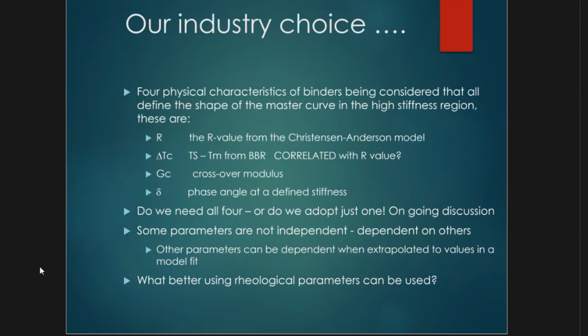And then we have the delta Tc. I think I've heard about that. The delta Tc, you can see here, is a difference between a critical temperature for the stiffness and the m-value. You measure these and you look at them and you come to a difference. I'll give you some examples of that.